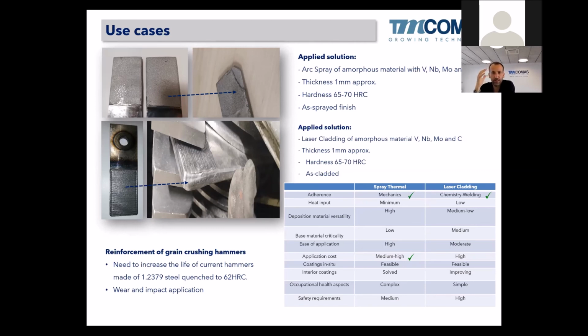So in theory, the life of the hammer has been increased by the use of laser cladding wear resistant coating in this case. So in this use case, we had the option to use laser cladding and thermal spray. Thermal spray was a cheaper application, but due to the impact that was higher than we expected, the coating has failed. So there's only the option to use a welding application. Okay.